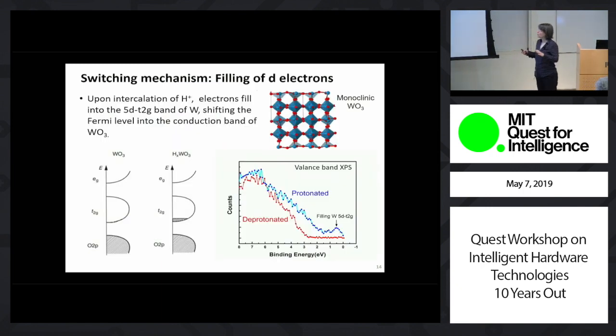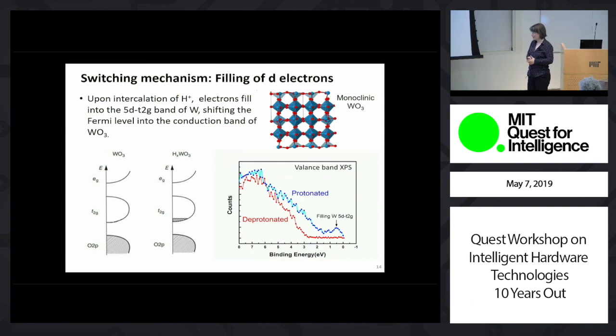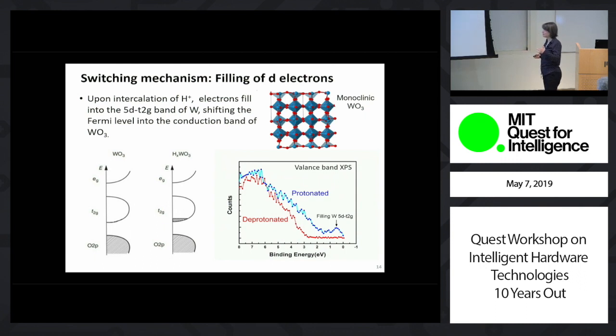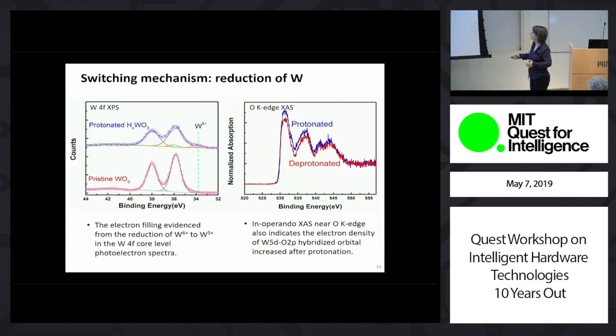Okay, so what I've shown to you was the electrical characteristics that we could obtain with this palladium hydride Nafion tungsten oxide system, and we have also looked into the mechanisms by which tungsten oxide switches its electronic conductivity upon protonation. Here I'm showing the valence band measured by photoelectron spectroscopy before protonation and after protonation, and that latter data shows us this new peak, which is indicating the filling of tungsten t2g states in the 5d band, which is consistent with electron donation to tungsten.